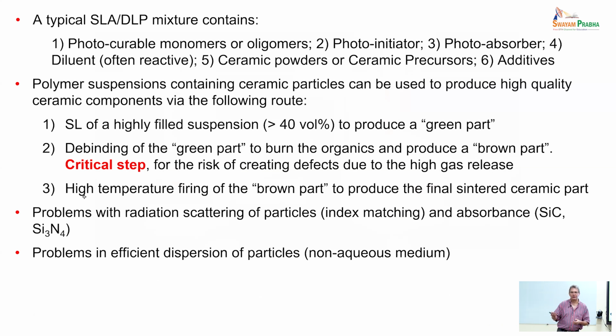So, of course, what you could do is to reduce the number of ceramic particles that you are using for your feedstock. But this means that in the end, your part will have a lot of polymeric binder that needs to be decomposed. And this leads to a lot of issues in terms of gas release, cracking, and also shrinkage, because the less solid ceramic particles you have in your system, the higher the shrinkage of the part, with issues in terms of shape stability, and also it's an issue of cost.